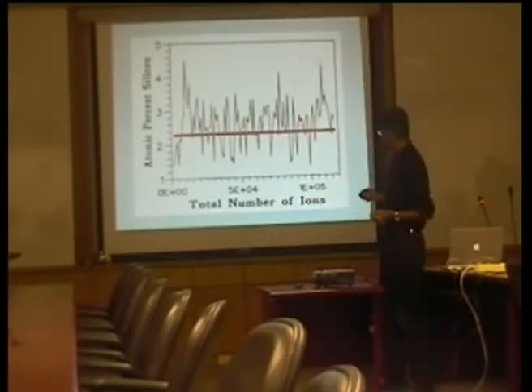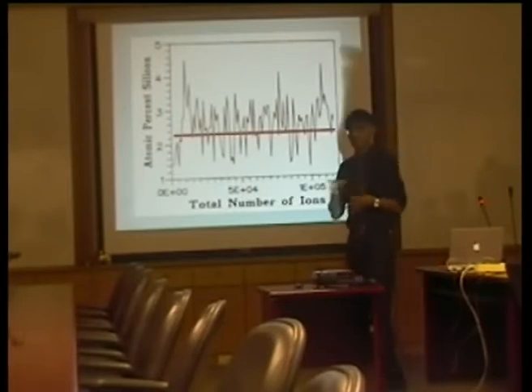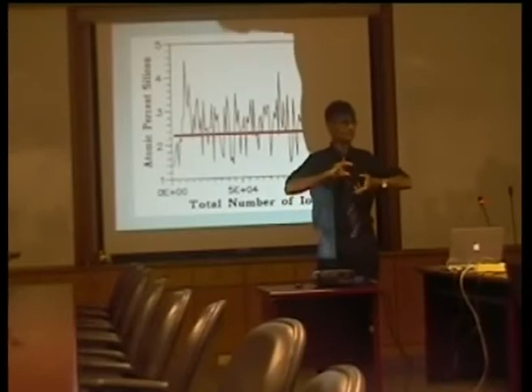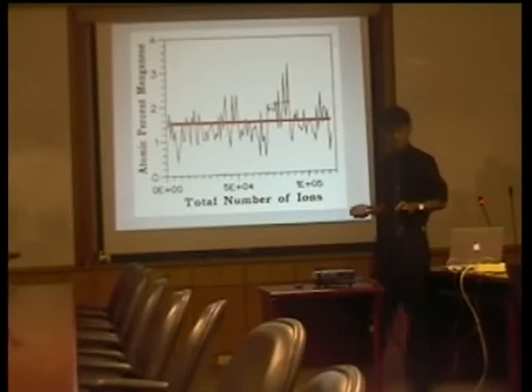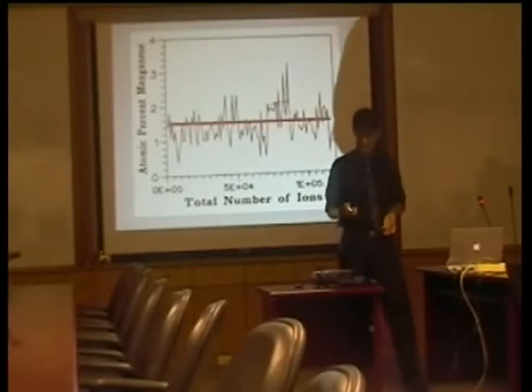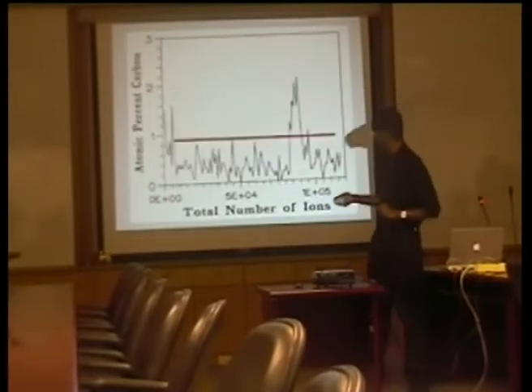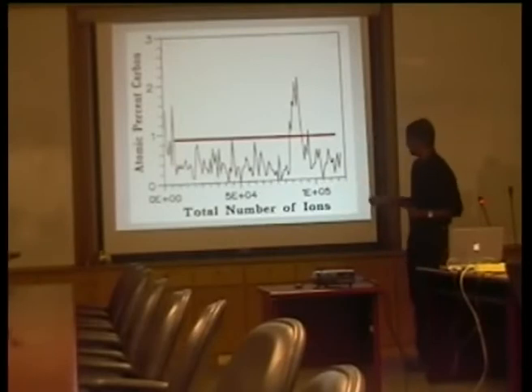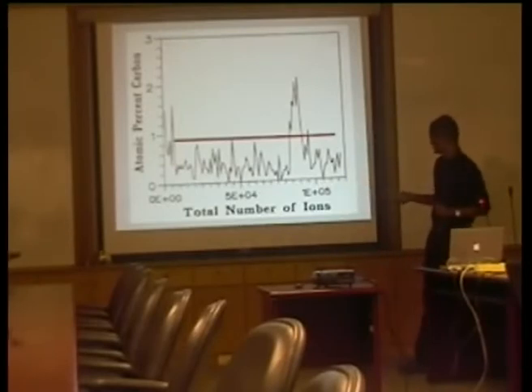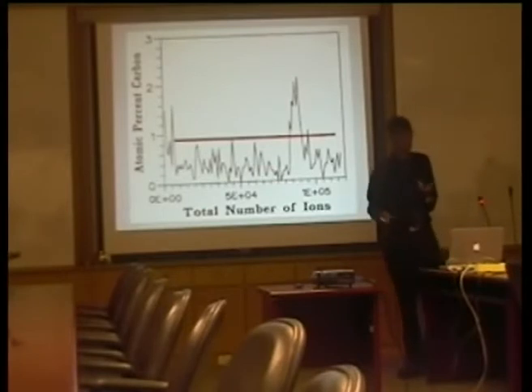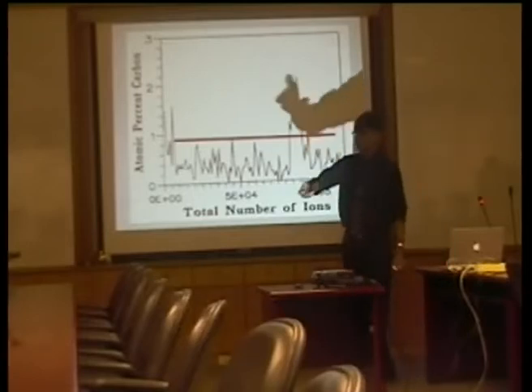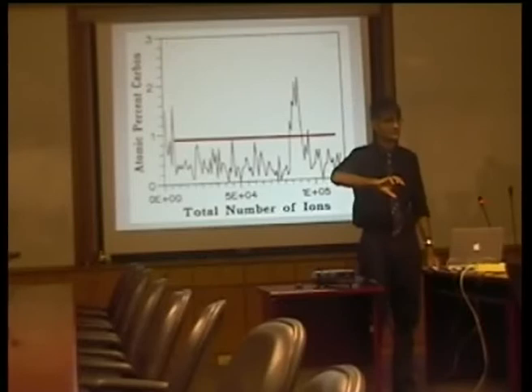What I'd like you to notice is that the average composition of the steel is this. So the silicon is homogeneously distributed between the ferrite and the martensite, even though we did the intercritical annealing. It's because this mechanical deformation has mixed the phases up. Similarly, the manganese is evenly distributed between the ferrite and the martensite. And surprisingly, if you look at the carbon, although the ferrite has less than the average carbon concentration, it still has quite a large carbon concentration forced into it by mechanical deformation. So we truly are mixing up the martensite and ferrite in the solid state.